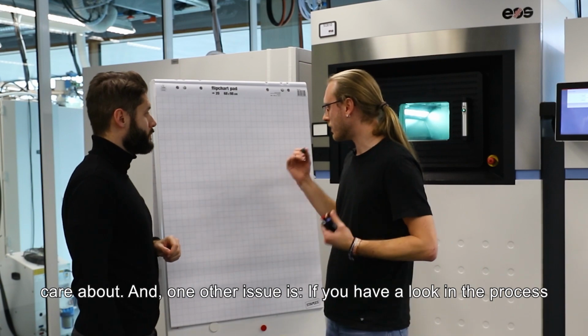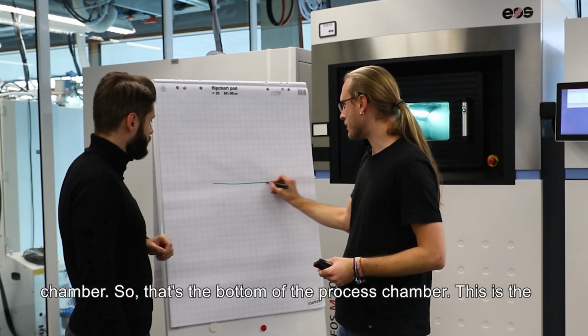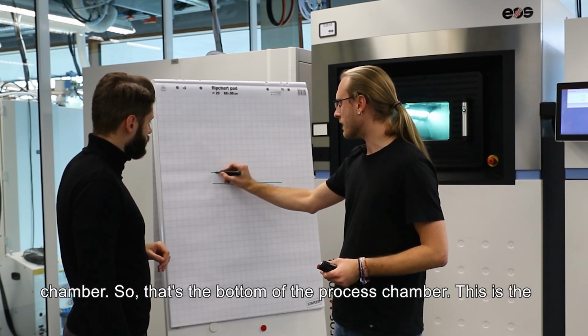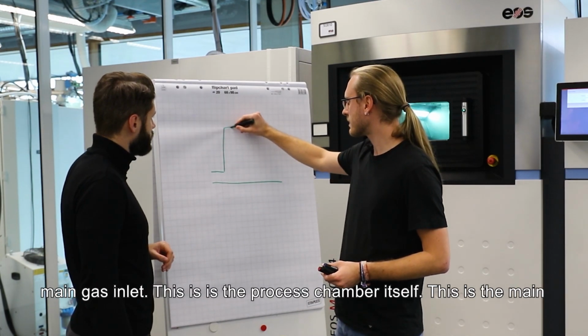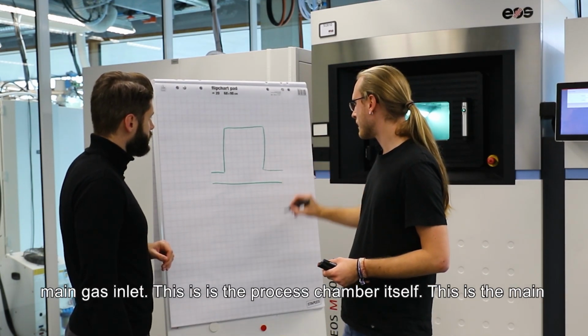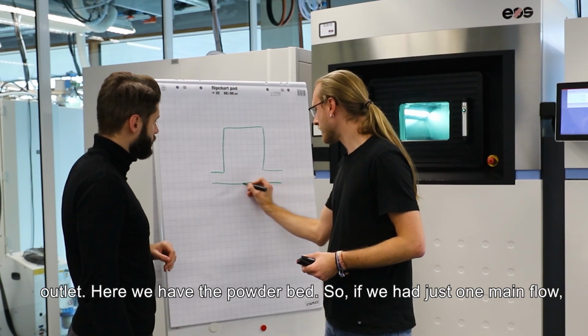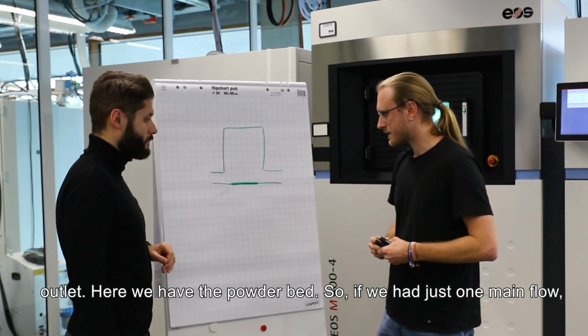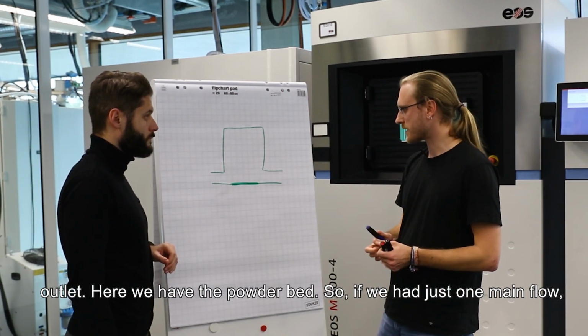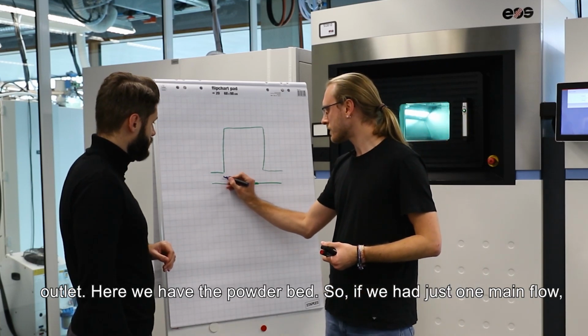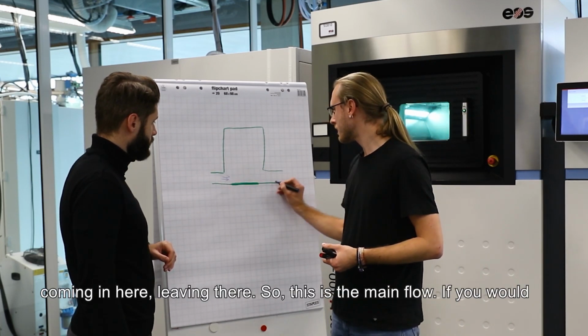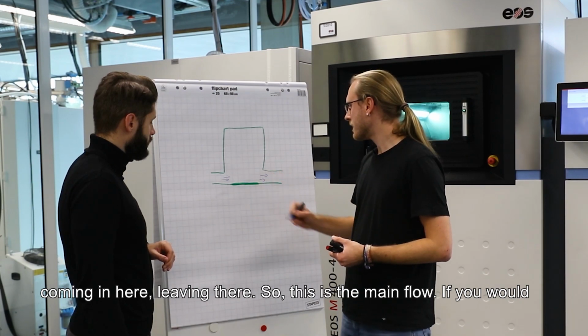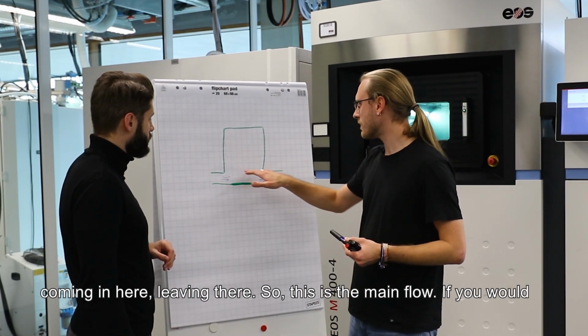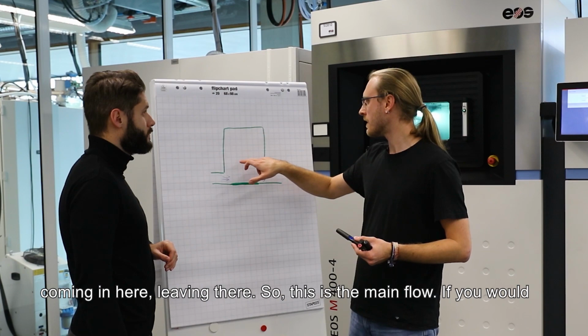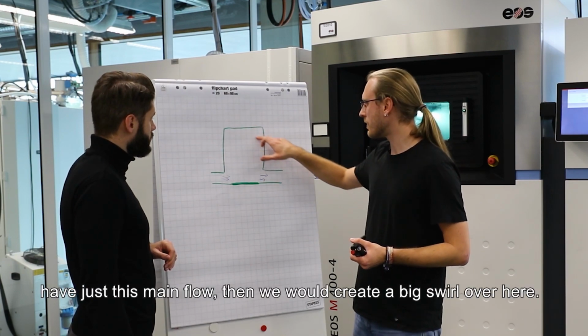if you have a look in our process chamber, so that's the bottom of the process chamber. This is the main gas inlet. This is the process chamber itself. This is the main outlet. Here we have the powder bed. So if we have just one main flow coming in here, leaving there, so this is the main flow. If you would have just this main flow, then we would create a big swirl over here.